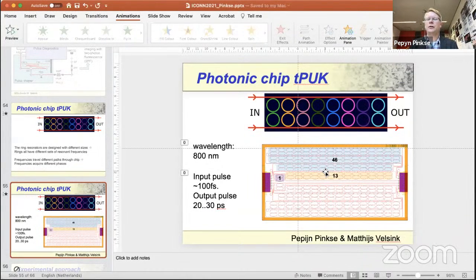I don't know of a better way of making this, and still I cannot make two resonators which are exactly the same. And we think this has to do with nano roughness of the edge of the waveguides, so that the effective index changes. But it can also be due to the fact that we are working with silicon nitride, which is an amorphous material. So I think there's also a fundamental limit, at least for this material, on how accurate you can produce a ring resonator. Of course, you can make a tunable one by putting a small heater on it.